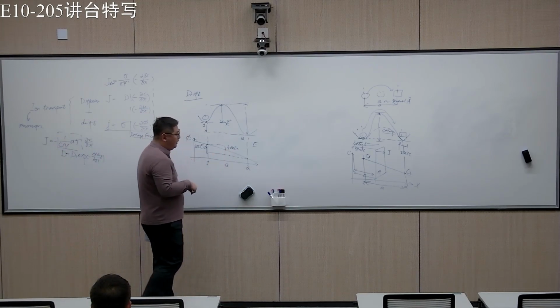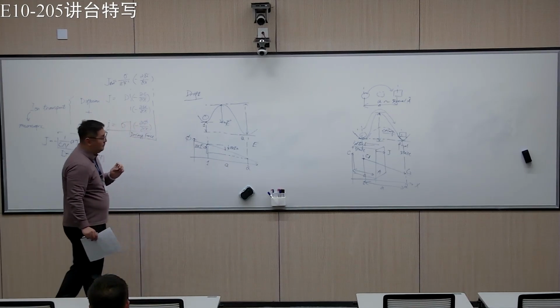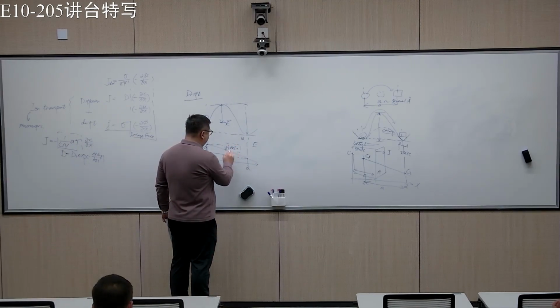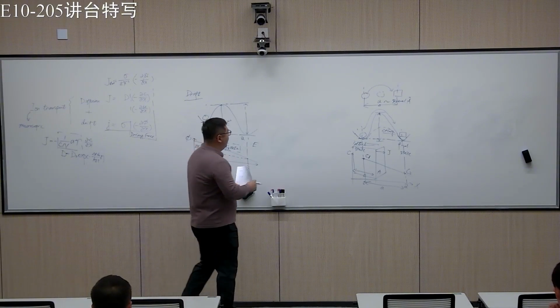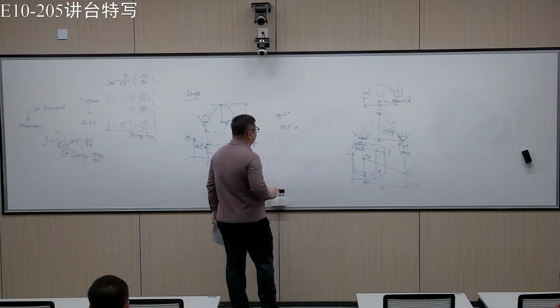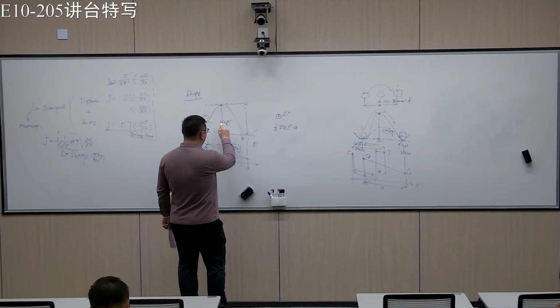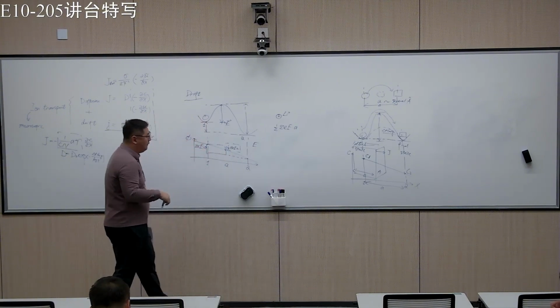What we are interested in is calculating, if we apply the electric field, how much it changes the energy landscape. First of all, let's see how big this thing can be. Since we are trying to change it, it's basically this term. For example, if we have a cation like lithium, then we have e times E times A, or half of that times A, because if you come from the middle, looking both ways, you have half of this value.